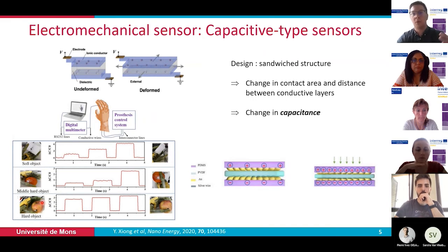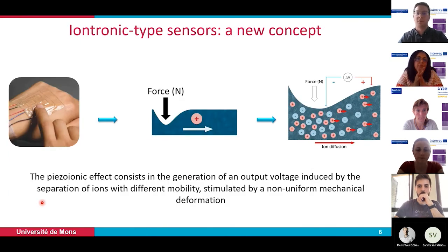So today I would like to introduce you to a new type of electromechanical sensor, which is called the iontronic type sensor. And these materials use the piezo-ionic effect. So it's materials where inside you have ions, and these ions have different mobility. And so when you apply a non-uniform deformation on these materials, due to the difference of mobility of the ions, you will have a separation of these ions, so a difference of concentration at different spots on the material. So this will lead to the generation of an electrical voltage that you can also measure.